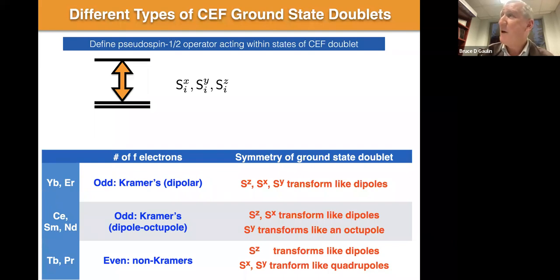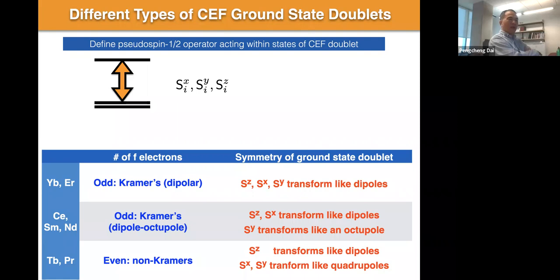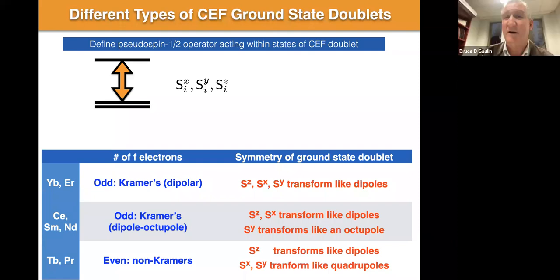Now, as those sorts of defects go, cerium 4+ is relatively benign because cerium 3+ has one 4f electron, cerium 4+ has none. So the defect that you're introducing is actually a magnetic vacancy, which is simpler, I guess, than if you were to introduce a different magnetic moment with a different anisotropy and different couplings and so forth. Bruce has a whole PRB paper talking about this. That's right. So there has been a fair bit of work.